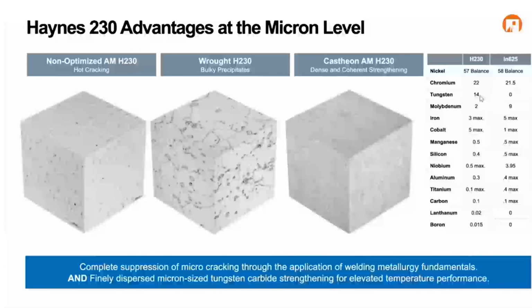You kind of see over here the difference in chemistry. Whereas in 625, a lot of molybdenum in there, and molybdenum is going to form these strengthening carbides as well as be a solid solution strengthener, here we have about 14 weight percent tungsten. That's going to act as a solid solution strengthener, and then also form those carbides.